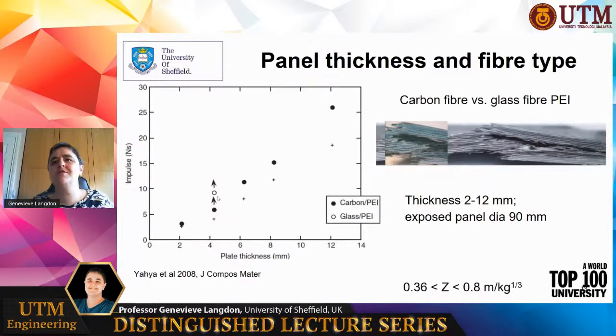And this has been quite a controversial point in the literature, and Yasir's PhD contributed greatly to our understanding of the fact that glass fiber was more blast resistant than carbon fiber in many applications. That's probably due to its increased ductility, whereas carbon tends to be slightly more brittle. Just out of interest, glass is also better than Kevlar.